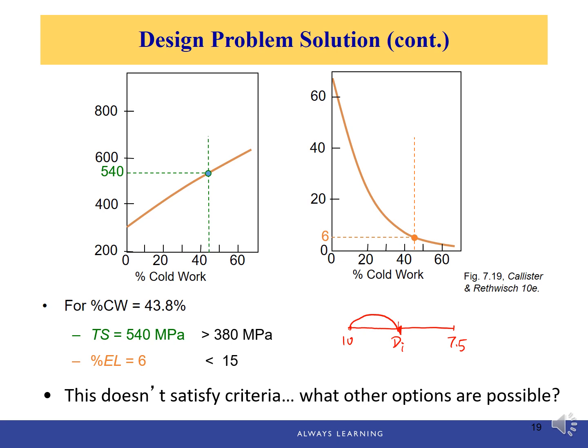After this cold work, stage 1, we do heat treatment. We recover the mechanical properties of the material, mainly to restore its ductility, and then we do the second stage, cold working stage 2. And the final property only depends on the percentage of cold work at stage 2. We just need to make sure the stage 2 cold work value will give us the desired resultant property. Then we will meet all of the criteria. Again, between those two cold works, we need to do annealing to restore all of the properties.